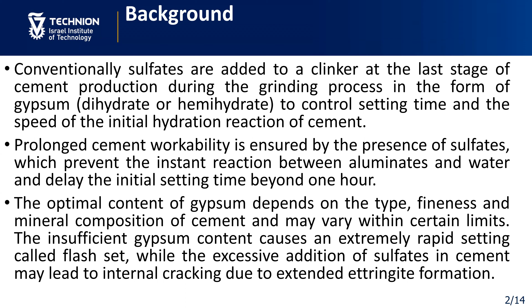The optimal content of gypsum depends on the type, fineness, and mineral composition of cement and may vary within certain limits. The insufficient gypsum content causes an extremely rapid setting called flash set, while the excessive addition of sulfates in cement may lead to internal cracking due to the extended ettringite formation.